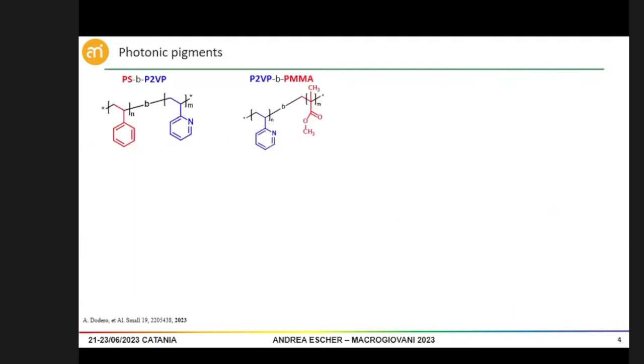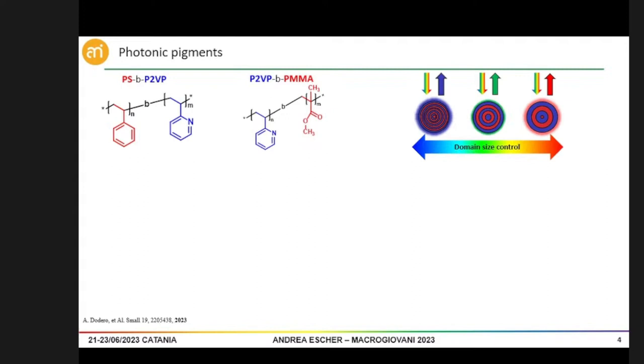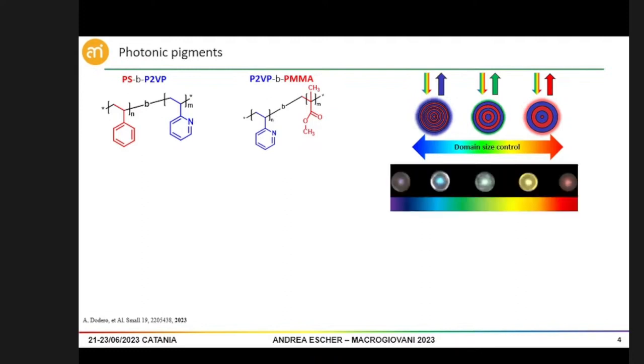So for my project, I use two different diblock copolymers. The first one is made with polystyrene and polyvinyl pyridine, and the second one is made with polyvinyl pyridine and polymethyl methacrylate. The idea is to tune the domain size of these pigments in order to tune them all over the visible range. I report here the optical image taken with the microscope, and we can see that the color goes from violet to red.